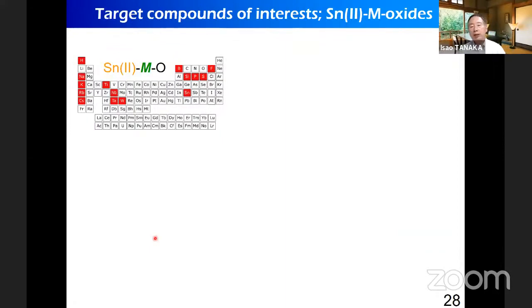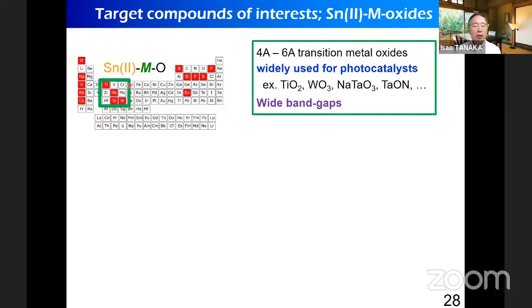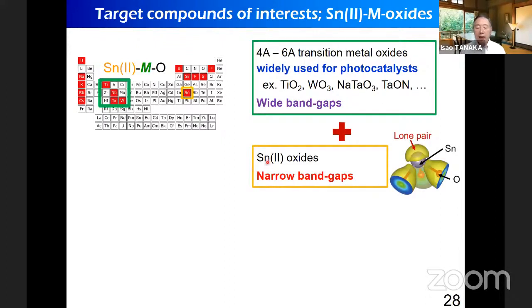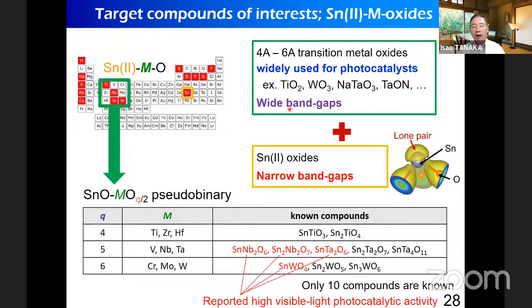The target compound of our interest is divalent tin with some other metals. There are many different kinds of mixed oxides with divalent tin. And among them, we will focus on the early transition metals because these early transition metal oxides have been widely used for photocatalysts, like TiO2. But TiO2 has a problem, it has a wide band gap, wider than the visible. And those divalent tin oxides have narrow band gaps. So a very naive idea is that by combining this type of early transition metal oxide with the divalent tin oxide, we may be able to find some good visible light photocatalysts.